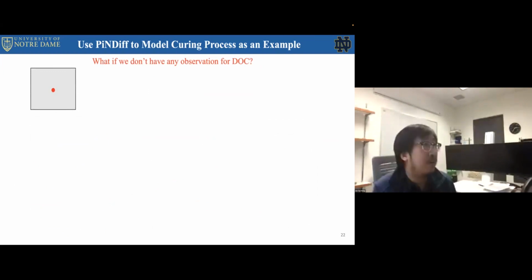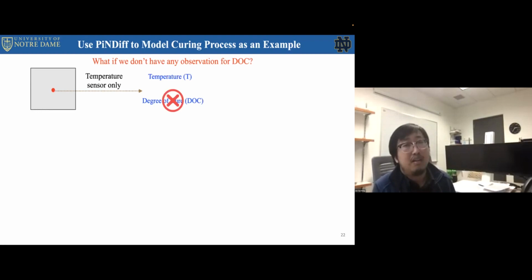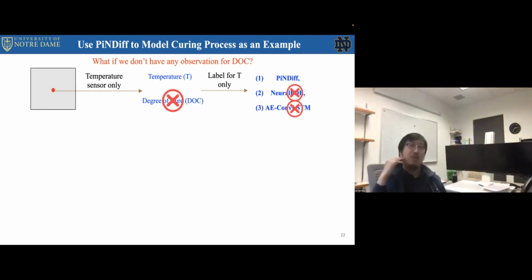Okay, so let's make it more practical, because in general, some physical quantities are easy to monitor during the manufacturing process, while others are not. In this case, we can easily measure the temperature. We can put in a thermocouple, right? So it's no problem. But how do you monitor the degree of cure? That is practically not easy or even not possible. So let's see if we only have the temperature sensor and no measurement for degree of cure at all. In this case, if you want to train models completely in a data-driven way, you can only train a model that predicts temperature, and you cannot predict the degree of cure.